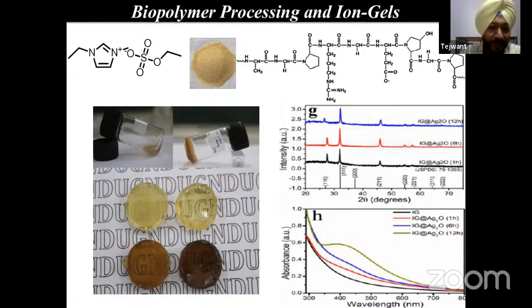So we have also tried gelatin, which is a protein devoid of any secondary and tertiary structure, for the preparation of ionogel. Ionogel means we tried to entrap the ionic liquid in the network formed by the gelatin polymeric chains. So what we have done, we have heated the ionic liquid and added the gelatin into that at around 60 degrees Celsius. Once you cool the solution, the solution becomes a gel. One can see in the photographs over there, in the right photograph, it's the gel.